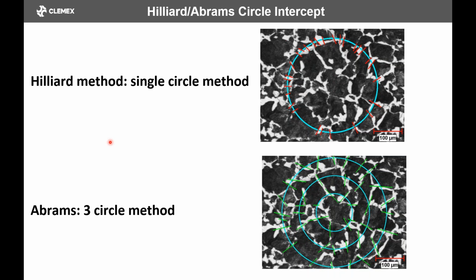Abrams improved that method by adding 2 other circles. The idea is to have more counts within a certain image, because there's a certain number of grains that you should use if you want something repeatable or statistically viable. So having 3 circles gives you more intercepts to count. It's also not limited as much as the manual planimetric method, where the grain size could be deformed. It doesn't need to be equiaxed because now we have a random method of counting the intercepts.